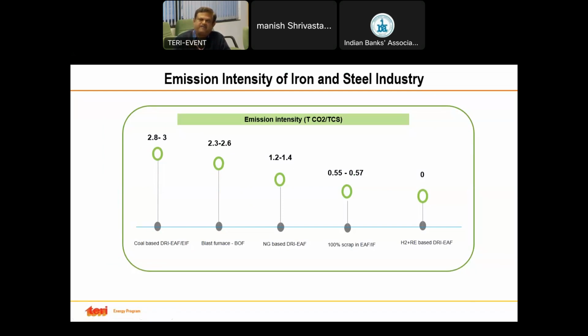So we have seen a diverse nature of the industry, both in terms of routes and energy consumption. In this slide, you can see how the emission intensities vary across the steel industry, depending on the route, technology or fuel mix used. On the first, the coal-based DRI, electric arc furnace, induction furnace route has a high emission intensity. This is defined in terms of tons of CO2 released per ton of crude steel produced in this route. It varies from 2.8 to 3 tons of CO2 per TCS.